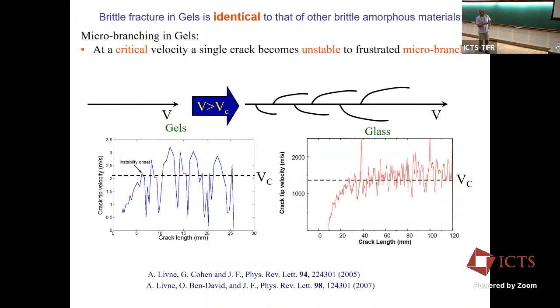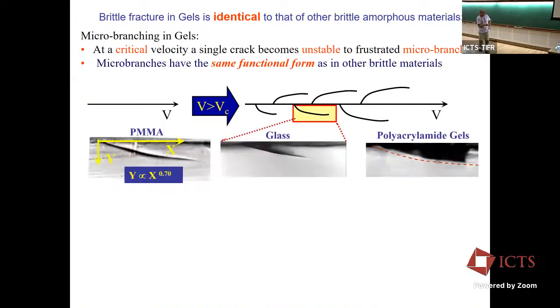okay, this is our instability. This is a crack. Here 0 is the beginning of the experiment. This is a comparison of brittle gels and glass. We have something that's relatively well behaved until it gets to about the same critical velocity, about 0.4 of the Rayleigh wave speed. And then it starts to wiggle, just as here. So we find that the dynamics appear the same.